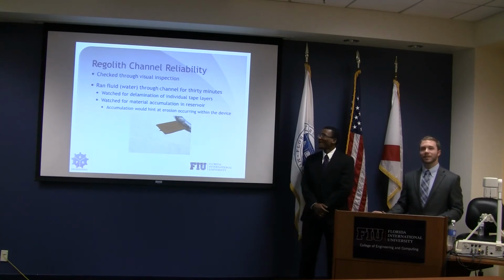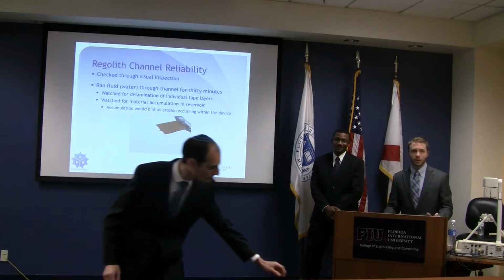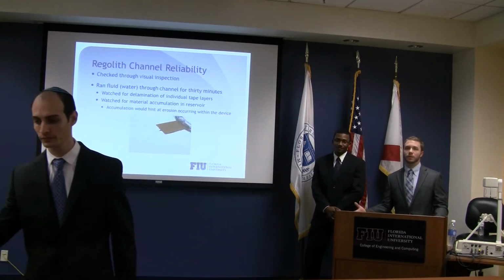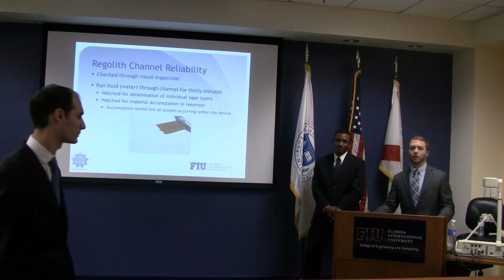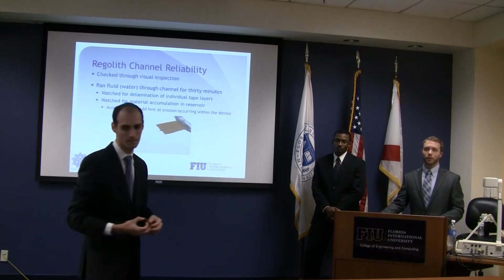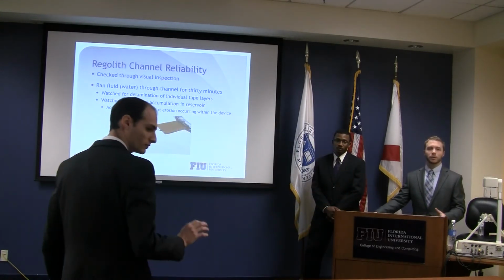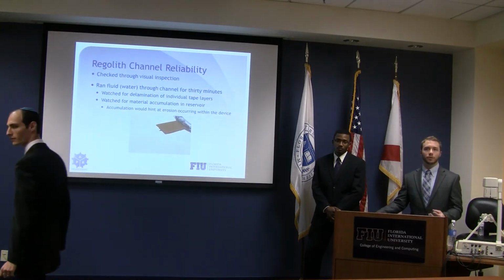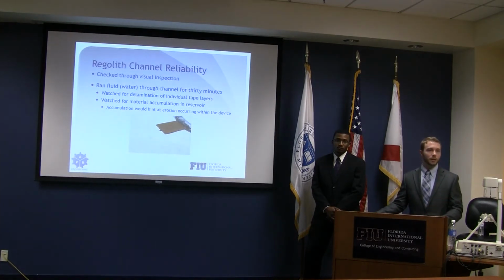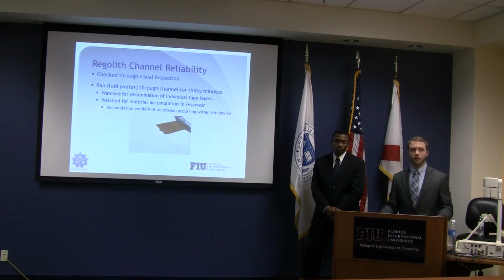All right, and the last thing that we tested was the reliability of the fluid channel that we made. We did this through visual inspection. We ran that device right there with a gravity pump for a period of 30 minutes, and we watched for delamination of the individual layers, as well as accumulation in the reservoir of individual particles that would hint at erosion of the interior channel. For the 30-minute period, we found no delamination, nor did we find any particles within the reservoir.